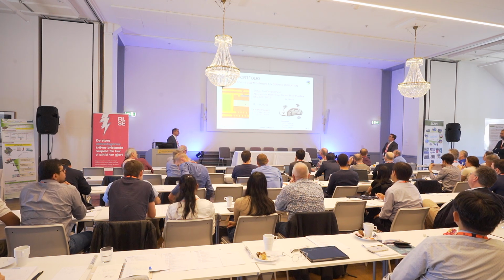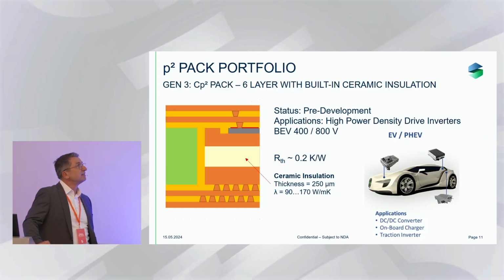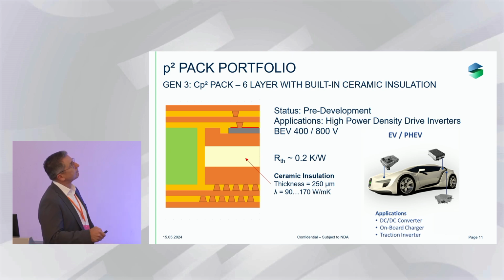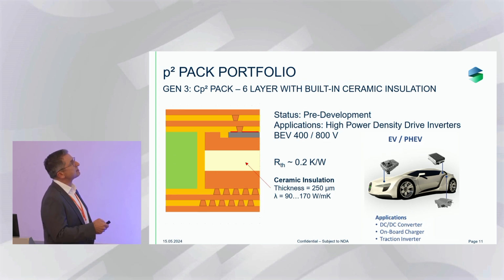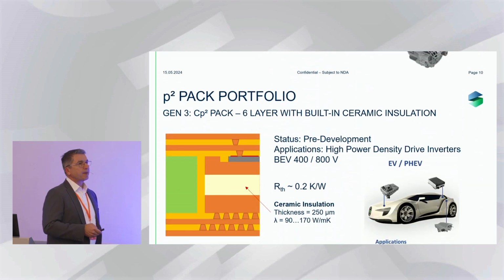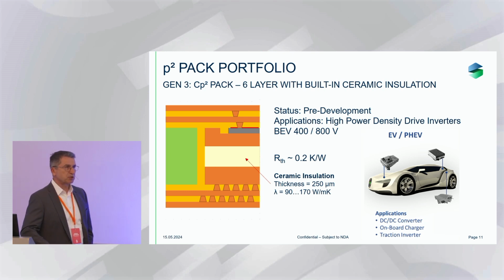Second question. Same picture, please. At a little bit higher voltage, like 1200 volt, the vertical insulation along the ceramic would not suffice in classical views. How do you assure that the insulation distance is enough in your organics? If you use a thickness of 250 microns here, you also have an insulation distance of 250 microns through the resin, which is covering the standard cell. So with 250 microns, you can have a very high blocking voltage. The typical material property is 40 kilovolts per millimeter. That means you are in the range of 10 kilovolts with a 250 microns insulation distance.